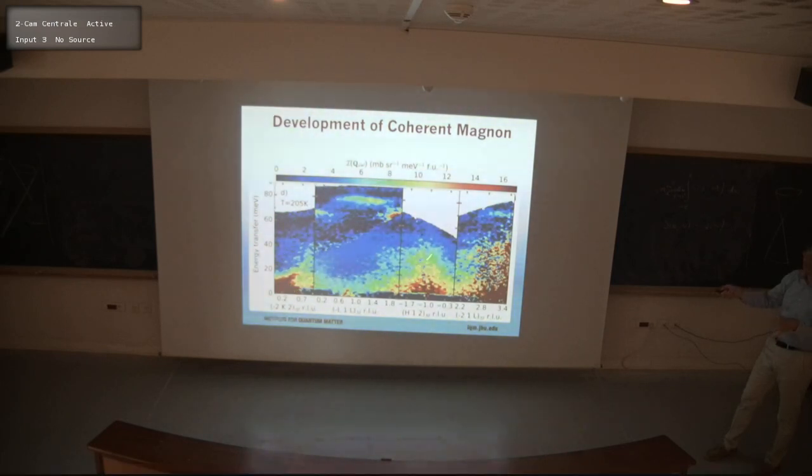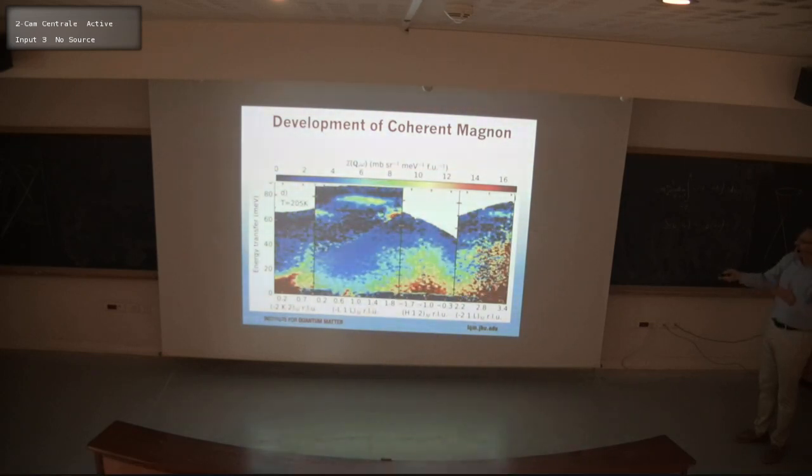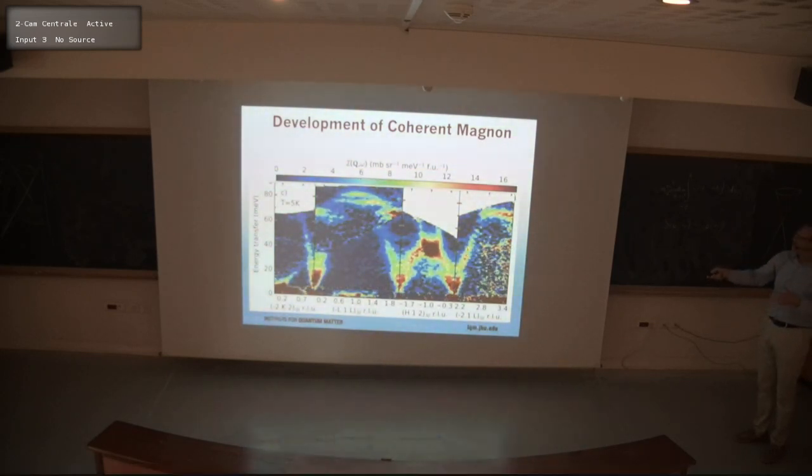So you see these broad features, not dissimilar, in fact, from what we see in these quantum spin liquid-like materials. They tend to have really broad blobs of intensity, if you will. Similar kind of stuff is what we're seeing. You now cool it down into the antiferromagnetic state, and from this morass, basically, you have the development of the coherent spin wave modes of excitation.